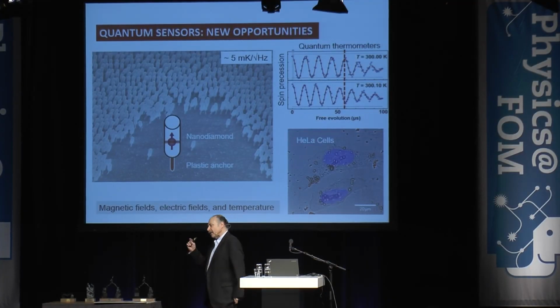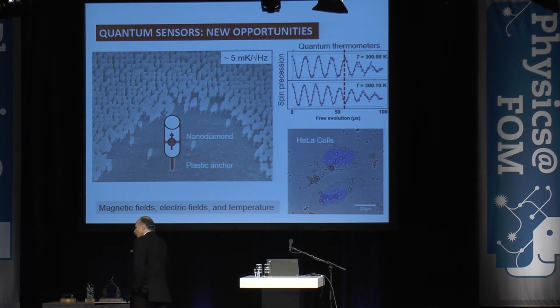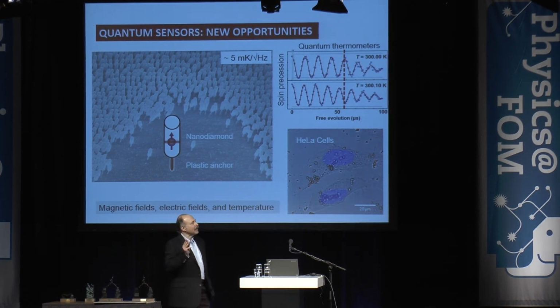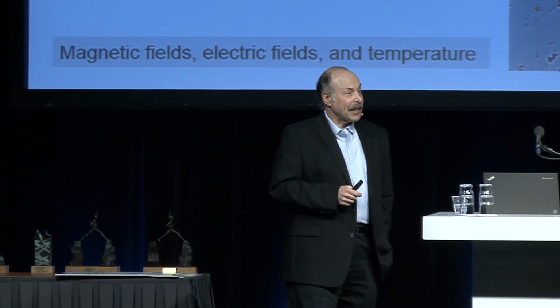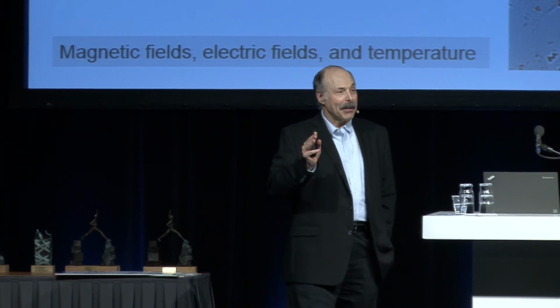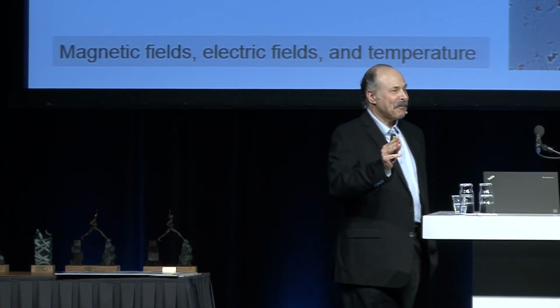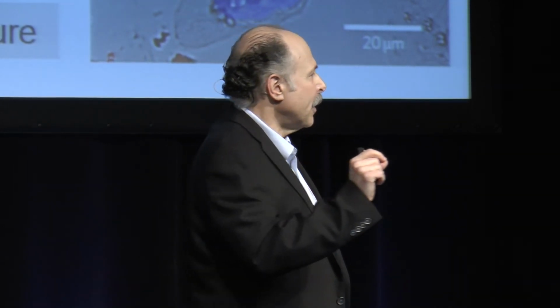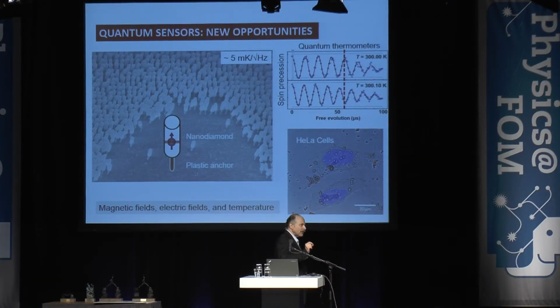One of the interesting things that came out of these measurements that students were doing is when they looked at a particular set of quantum probes every day, they saw that in the way we were doing this particular measurement, there was a little bit of a change in the frequency every time they measured. And at the end of a couple of months of looking at this carefully, they discovered that, in fact, the quantum mechanical wave function, if measured in a certain way, was incredibly sensitive to temperature. So the students came and said, this is a disaster. I said, no, the beauty of physics is that one person's disaster is another success story. That's not a liability. That's now a quantum thermometer. And in fact, it turns out they're extraordinarily good thermometers. You can see a part in the 10 to the 5th at room temperature just fine with these quantum probes.